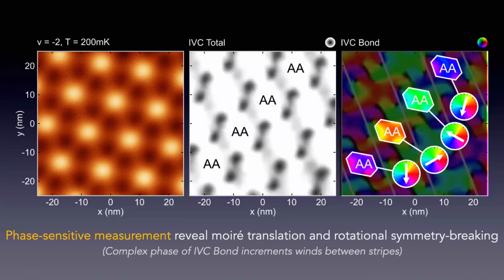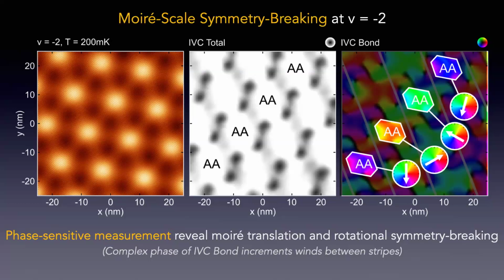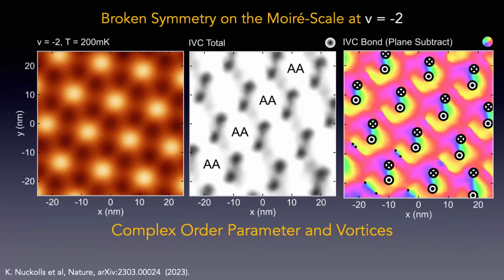Okay. So it turns out, and this is sort of the punchline of this whole thing, that there are many nearby states. And if we choose one state over the other, it turns out that this state is the one most favored and is found theoretically. We can have it even in small amounts. Okay, so if you look at this data, there is this phase gradient. So I asked the students to subtract the plane of phase from this data. And what they discovered is that underneath that phase gradient, if you remove it, there are objects that look like vortex, anti-vortex pairs in this IVC order.